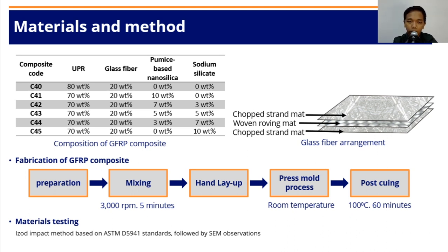In the fabrication process of GFRP composite, a 3000 rpm stirring process was performed for 5 minutes to do the mixing process between matrix and filler. The catalyst was added just before pouring it into the mold. Glass fiber types of chopped strand mat and woven roving mat are used in the arrangement as shown in the picture beside the table. The fabrication process was executed by the hand layup method followed by a press mold process which was performed at room temperature.